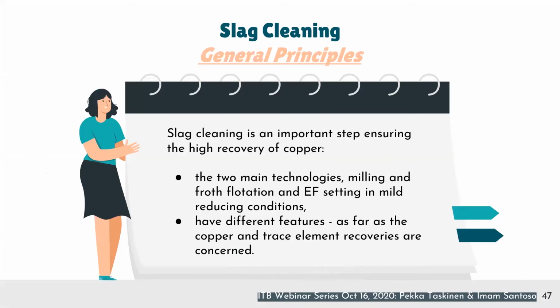And I have a few words about the last step of the primary smelting or flash smelting, because it is producing slag which must be treated because of copper recovery. So slag cleaning is ensuring the high recovery of copper also in flash smelting. So there are two main technologies: milling and flotation, and EF reduction, mild reduction, settling, and they have some importance in trace element distributions and recoveries, in addition to the copper recovery as well.